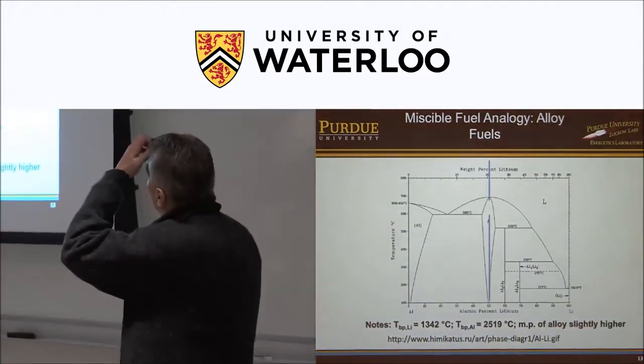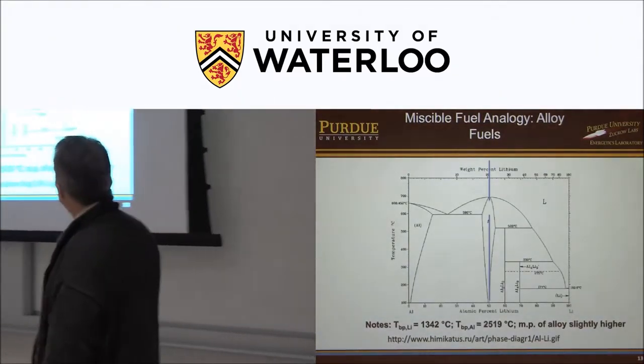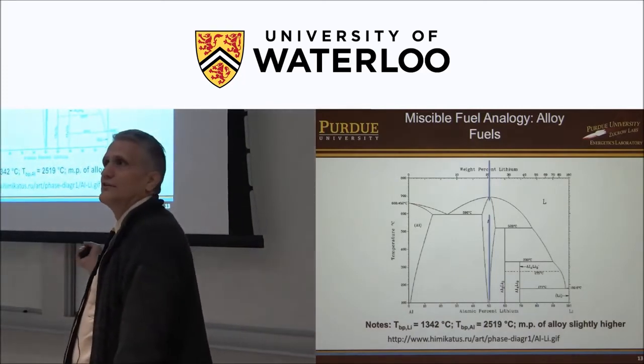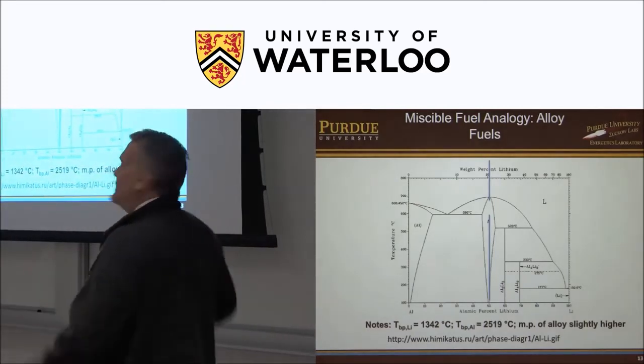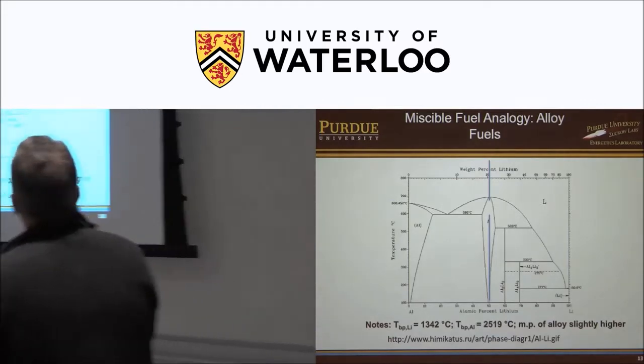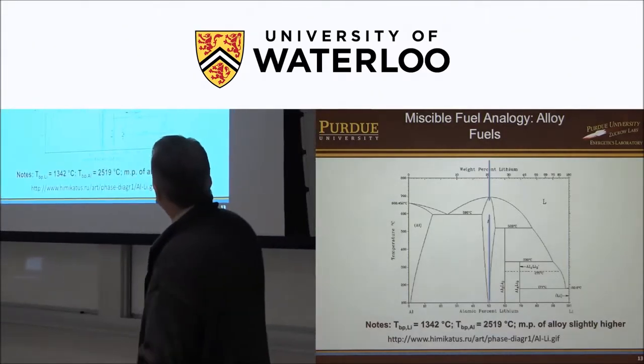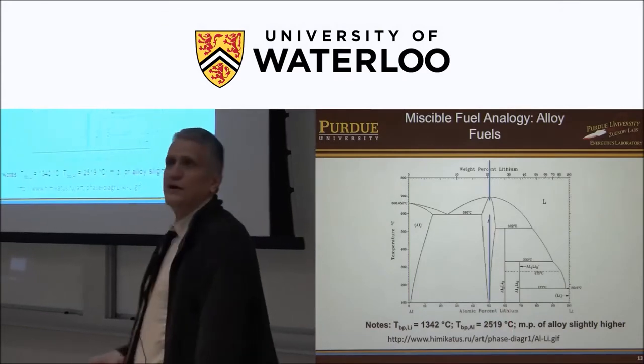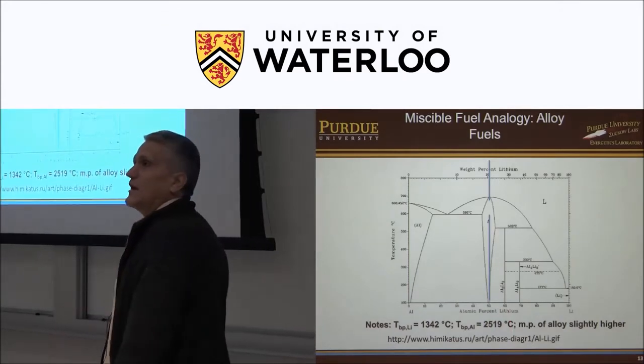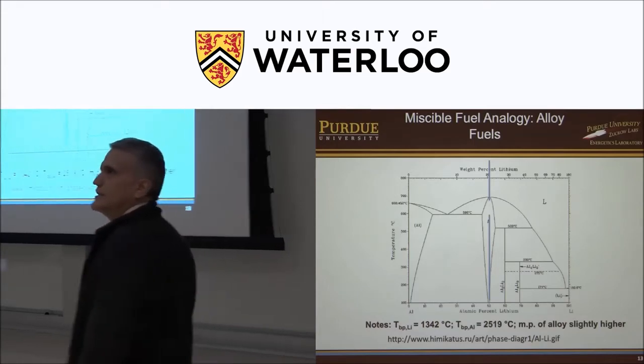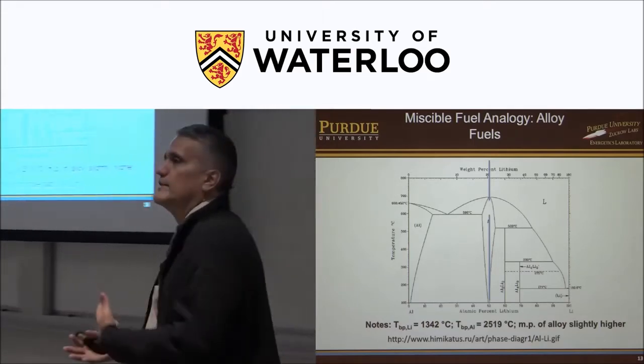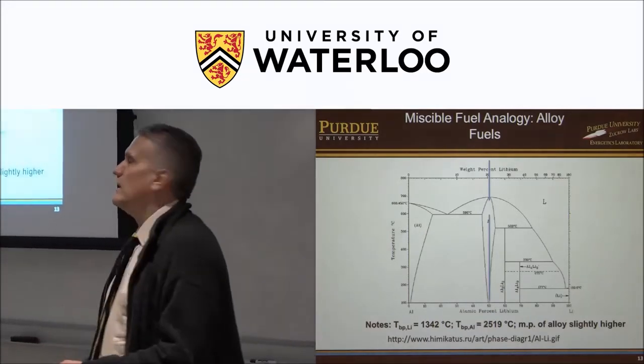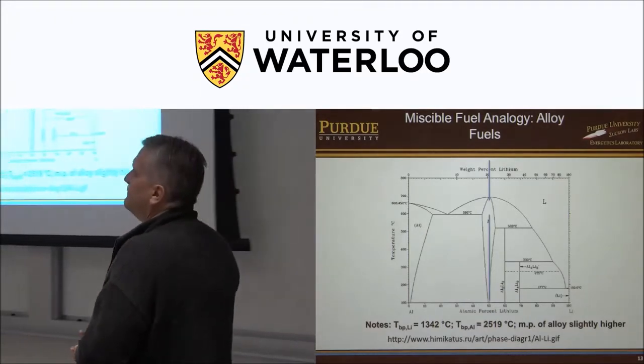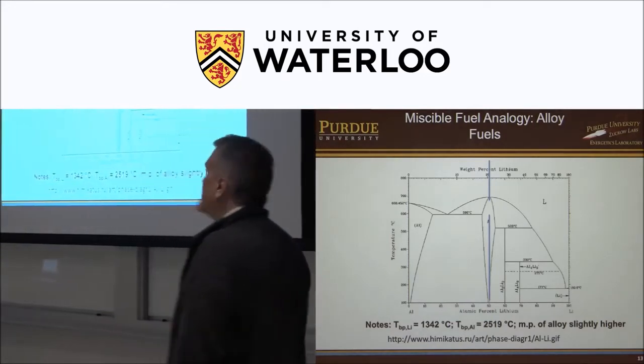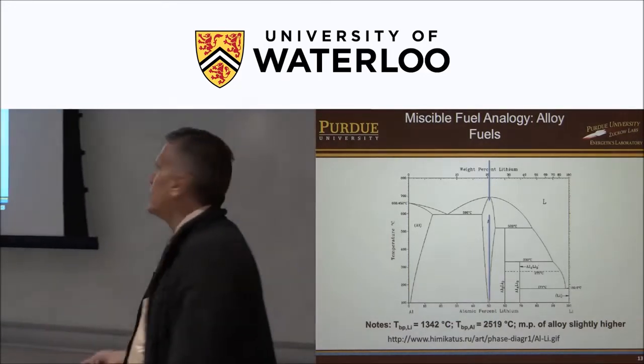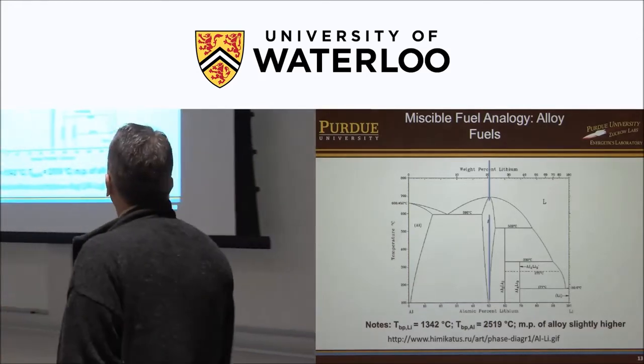As I mentioned, we also have looked at alloys. There's some of you in materials engineering, right? So you guys love these kinds of plots, right? These phase diagrams. And for the materials engineers in here, we're looking at a 1-to-1 atomic aluminum lithium. That's a lot higher content of lithium than what you normally see in a structural material. Usually for structural aluminum lithium, that's on airplanes we fly on, maybe under 5% lithium by weight. In this case, it's 20% by weight. Lithium's lighter than aluminum, but it's 1-to-1 atomic, forms a very nice alloy.